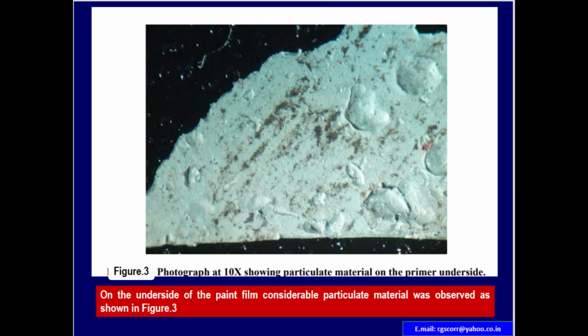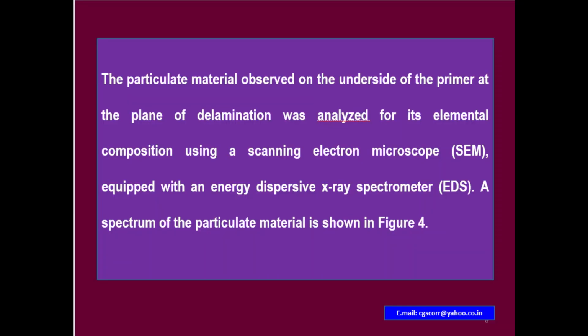Figure 3, 10 times magnified, showing particulate material on the primer underside. On the underside of the paint film, considerable particulate material was observed, as shown in figure 3. The particulate material observed on the underside of the primer at the plane of delamination was analyzed for its elemental composition using a scanning electron microscope equipped with an energy dispersive X-ray spectrometer. A spectrum of the particulate material is shown in figure 4.